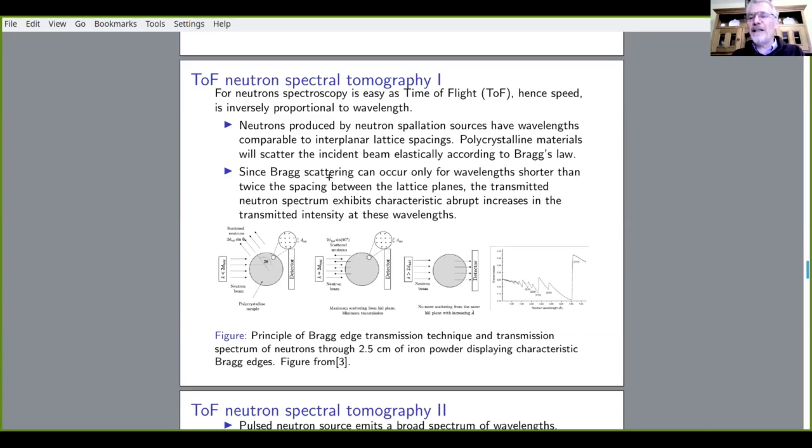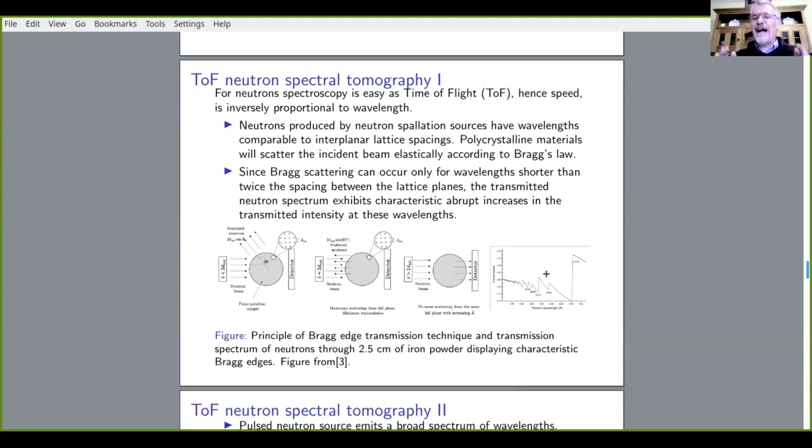The interesting thing is that we look at stuff that's mainly, to some extent, crystalline, and even if it's polycrystalline, like a metal, each spectrum tends to have a rather interesting structure like this. What happens is a lot of the neutrons that we lose in a crystal are lost by Bragg diffraction. Otherwise, they go off somewhere else, and we're nowhere near our camera, and we don't detect them. So that just looks like lost neutrons. But the point is, the Bragg angle is related to the spacing of the planes of atoms in our crystal.